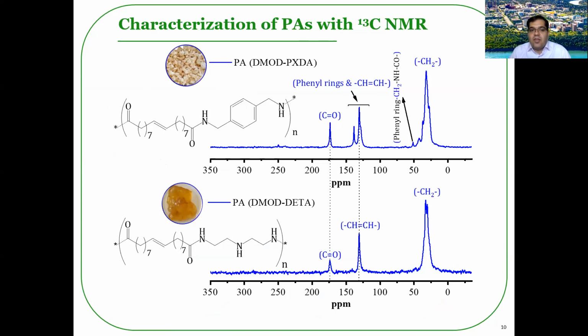According to the solubility issue of the polyamides, the carbon NMR spectroscopy was used to characterize the chemical structure of the polyamides. As you can see in the spectra of the polyamides, a peak at 174 ppm in the lowest field of the spectra is raised due to the presence of the carbonyl groups in the chain of the polyamides. In addition, a peak at 131 ppm of both polyamides spectrum belongs to the unsaturated motif of the polyamides.